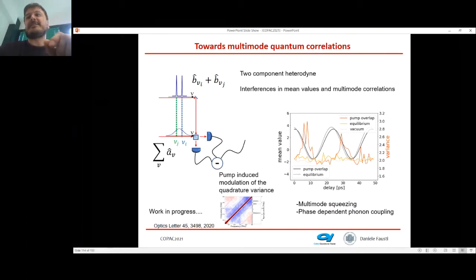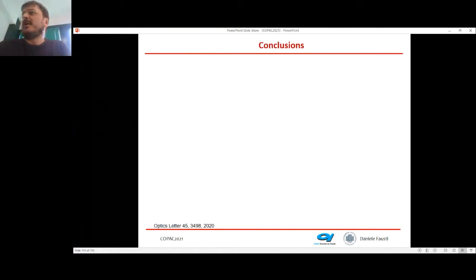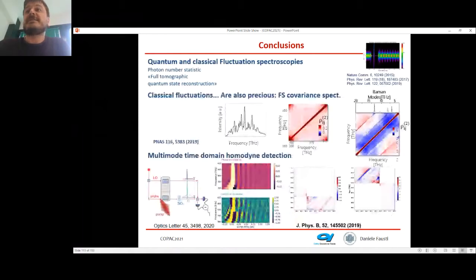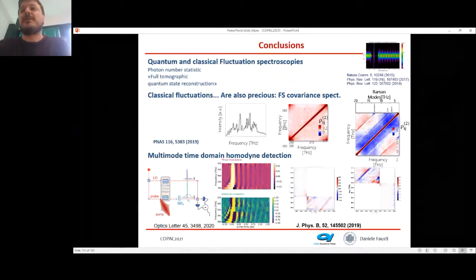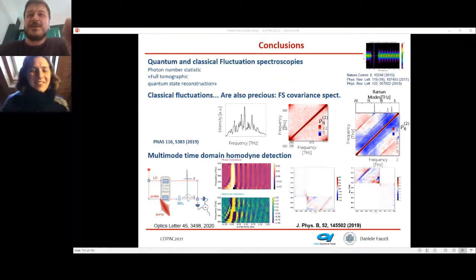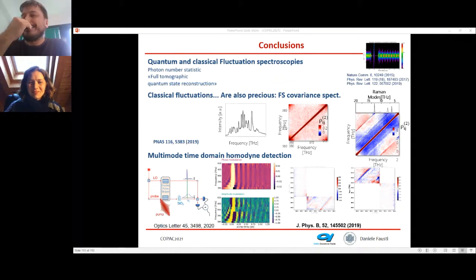And we have some evidence that we may have correlations also at the quantum level, as we did classically, and this would be pretty interesting to try to measure the intrinsic fluctuation properties of the atomic position, and so the fluctuations of the elastic field, just by measuring how the atoms move in the potential and how strong the potentials around the atoms are, just by measuring the fluctuations that they have in a dynamical response. I'm sorry I've been cutting it a bit short, but I think we can conclude here. Thank you. I think it's an interesting direction to go.